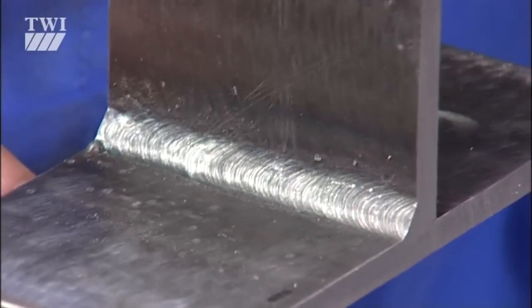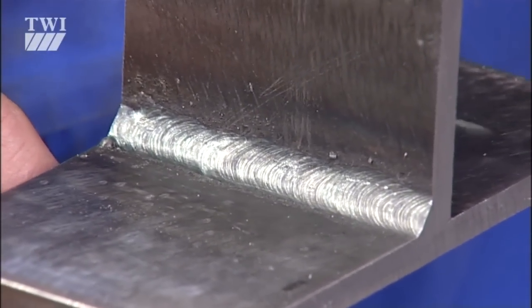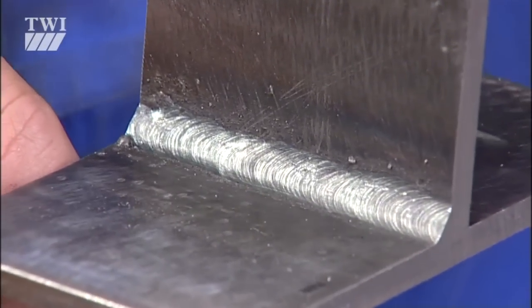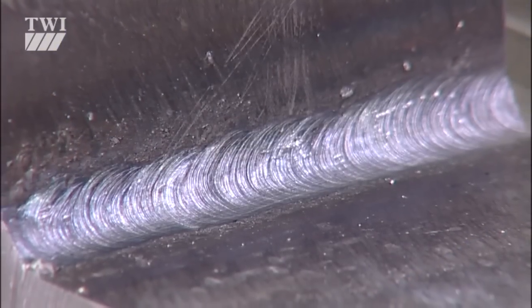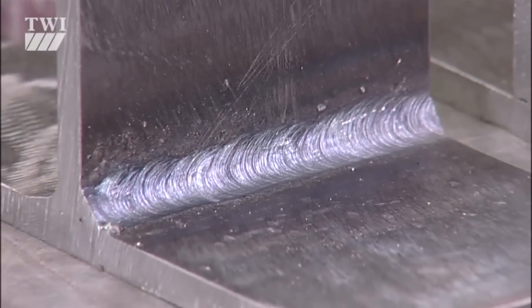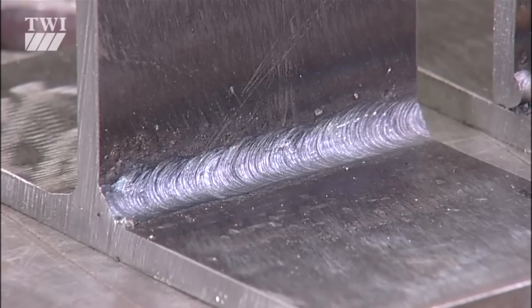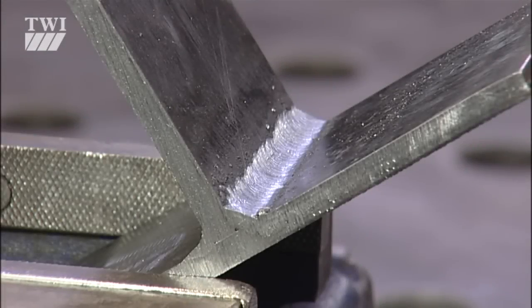Finally, the fillet fracture or weld break test. A simple and very crude test to examine a weld's soundness, often in a production environment on the shop floor. Two plates are welded together on one side only, in a T configuration. Of course the base metal, weld metal, and welding parameters must adhere strictly to those prescribed in the welding procedure under scrutiny.